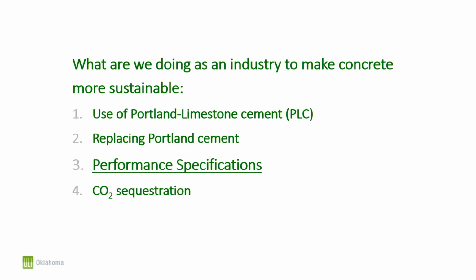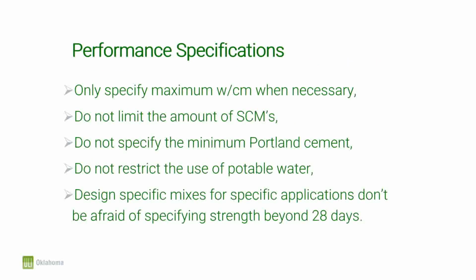Performance specification. I think this is where we can work hand in hand and help improve this carbon footprint. Caleb was talking about it. We always over-design everything that we do, no different in the concrete industry. I always over-design my concrete mixes, so my 4,000 PSI mix, my 3,500 PSI, per code, they always break above what I need in order to achieve my 4,000 PSI 90% of the time. Even in the equations, we calculate the level of low breaks, and we set it at about 10%.